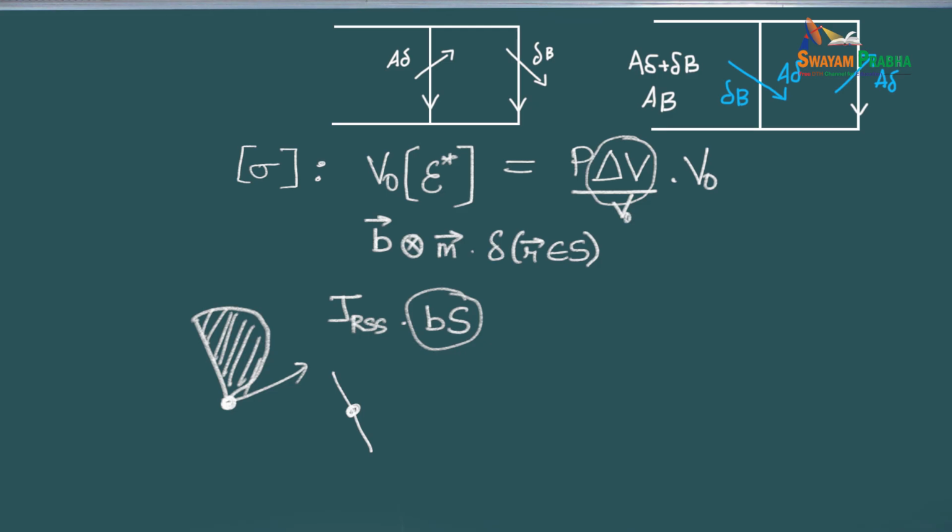So it's a relaxation volume in the sense that it's the change of volume the vacancy will have as it evolves from its initial configuration, where it has the volume in the matrix, to the volume it would like to have. Usually it doesn't go that far. That's physically the meaning. With dislocations, the activation volume is related to how much the dislocation will bend before it can unbend.